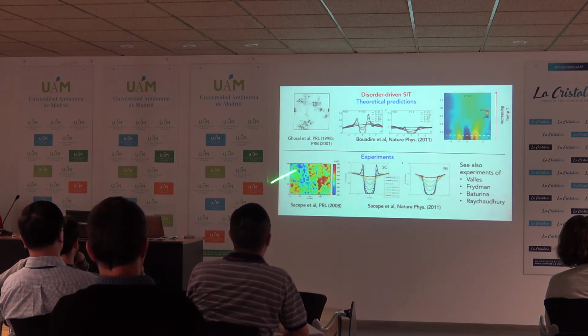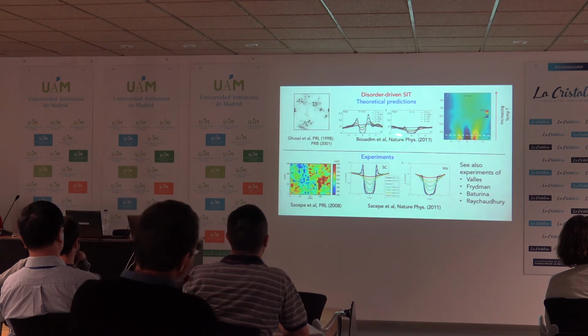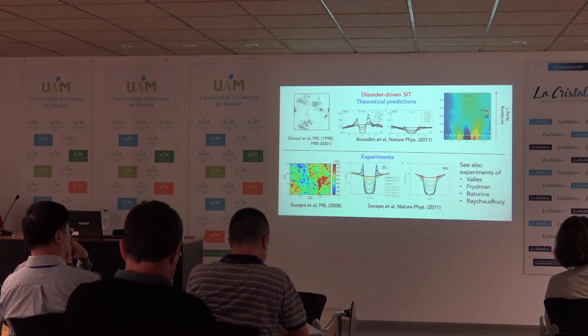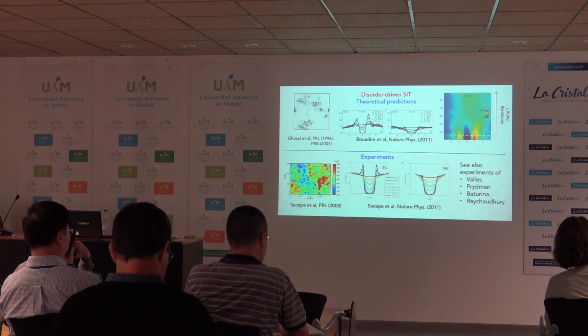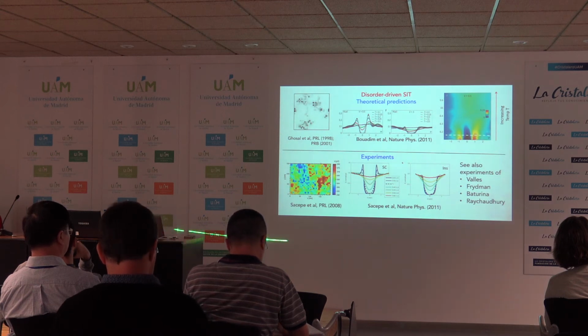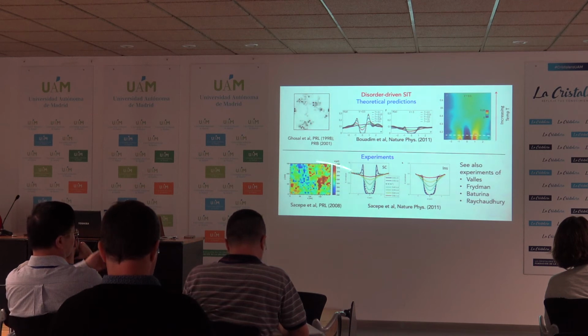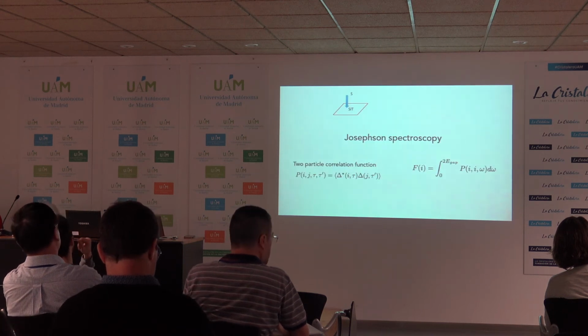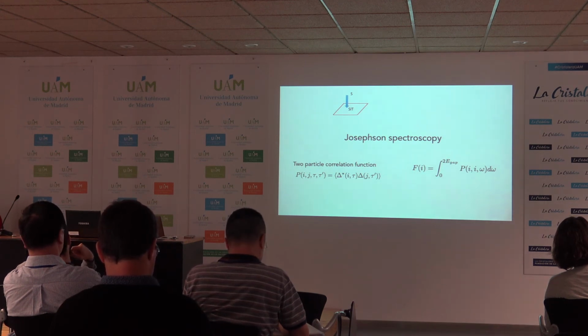So far, this is what I showed you from the theory. They have also mapped out, they cannot measure the local pairing amplitude, but they have looked at where the coherence peaks are sharp, and they see these kinds of patches forming at a particular sample.